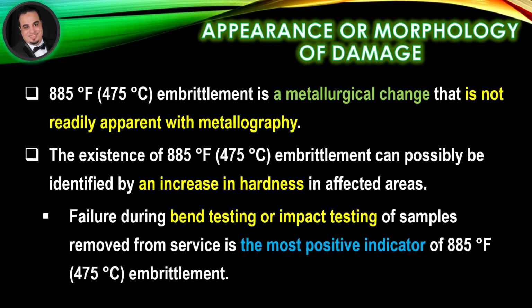Appearance or morphology of damage. 885 degrees Fahrenheit embrittlement is a metallurgical change that is not readily apparent with metallography. The existence of 885 degree embrittlement can possibly be identified by an increase in hardness in affected areas. Failure during bend testing or impact testing of samples removed from service is the most positive indicator of 885 degrees Fahrenheit embrittlement.